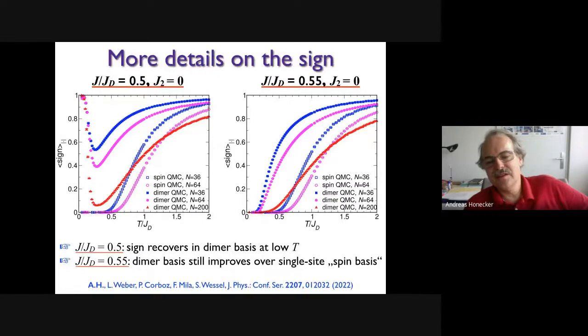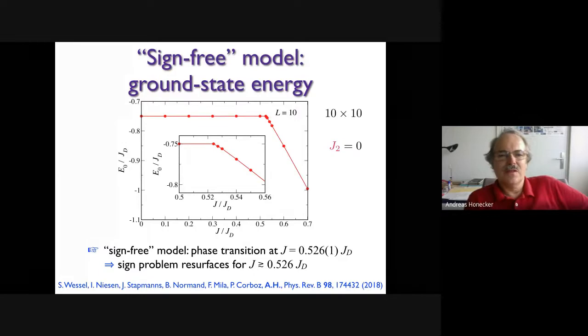But even for the 200 spin system here, the sign is still significantly better at low temperature than for the smaller systems in the single site basis. Okay, before I actually show you results obtained with that, let's ask what is going on here. We were actually a bit disappointed. The left is good, but the right we didn't like. And what is going on here?